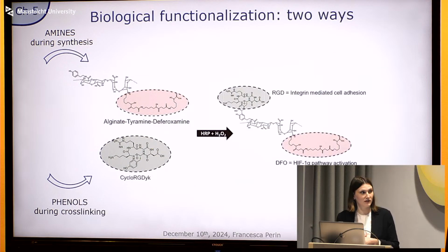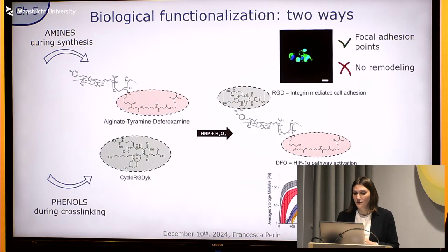We selected 2 model molecules for this approach. For the amines, we selected deferoxamine because it's a very well-known and studied hypoxia mimicker. And for phenols, we selected a commercially available RGD with a pendant phenol molecule. We found that the RGD was actually successfully introduced, and the cells were forming focal adhesions. And we also found that the deferoxamine preserved its chelation properties. But unfortunately, we also found some issues. So the cells were not able to properly colonize the hydrogels because they couldn't really remodel them. And also the deferoxamine really heavily interferes with the HRP cross-linking.